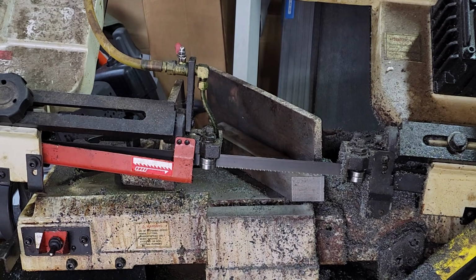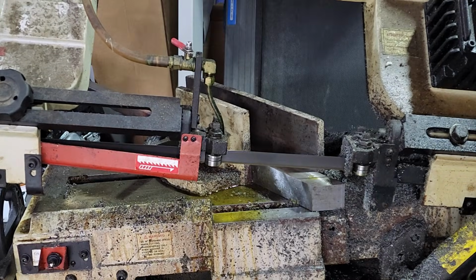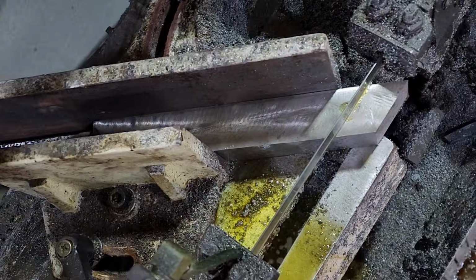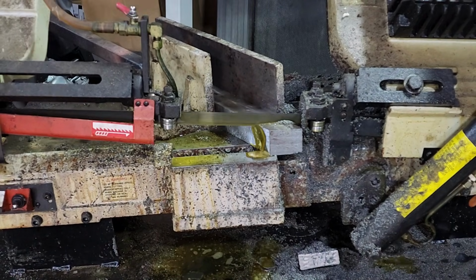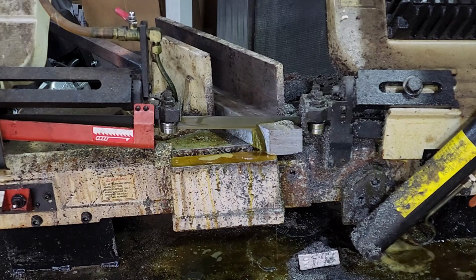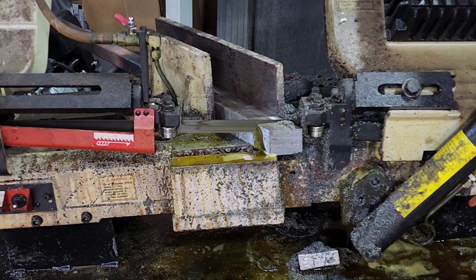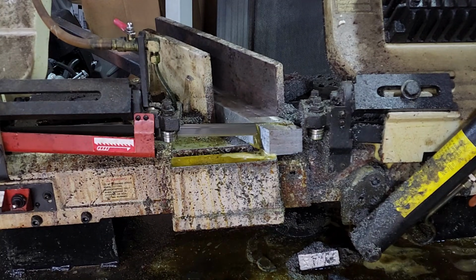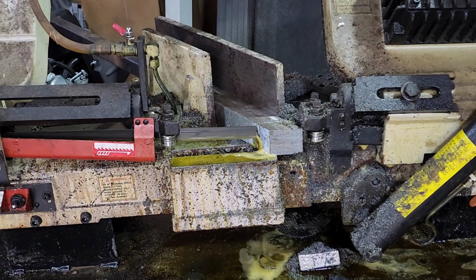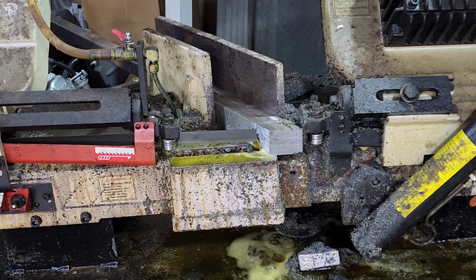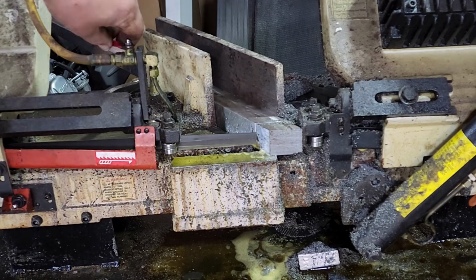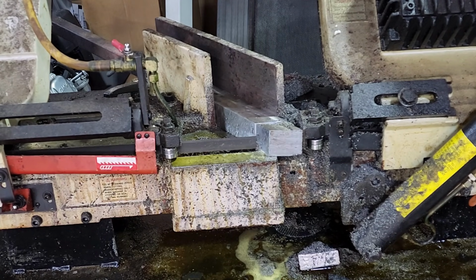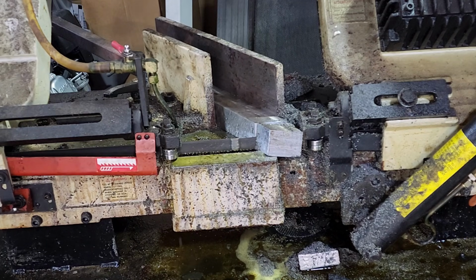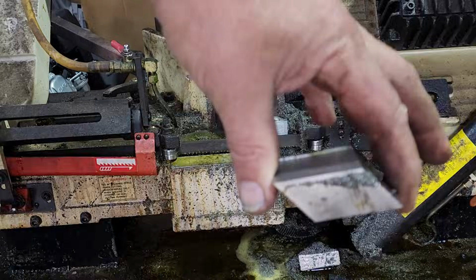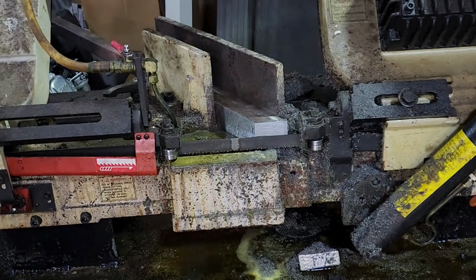We're chopping the square bar into 3/4-inch chunks at a snappy 42-degree angle. Think of it as giving the steel a stylish haircut that actually serves a purpose. You can play around between 35 and 45 degrees and still come out swinging. But back when I was slumming it at 35, my forge welds were flaking out more often than a bad blind date. And let me tell you, after dumping a solid week into hammering that monster billet down to this bar, a weld failure hits like a betrayal from your own hammer. It'll have you eyeing the nearest sharp object for a dramatic exit, samurai style. Except the blade doesn't exist yet because, well, epic fail. So I cranked that angle up to 42, and bam, 0 flops since.